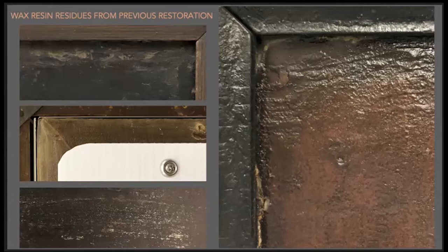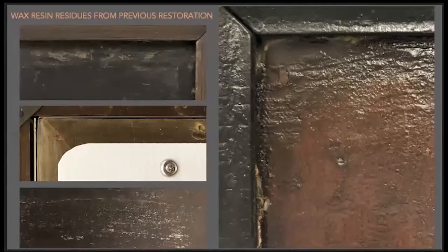The wax was applied generously, and globs of yellowed wax resin were visible along the edges and reverse of the paintings. The detail image in the center on the left shows a thick application of yellow wax resin on the reverse of a lining canvas. In these examples, the wax resin appears yellow and ranges in stiffness from a soft, crayon-like wax to a hard adhesive, depending upon how much resin was mixed prior to application.